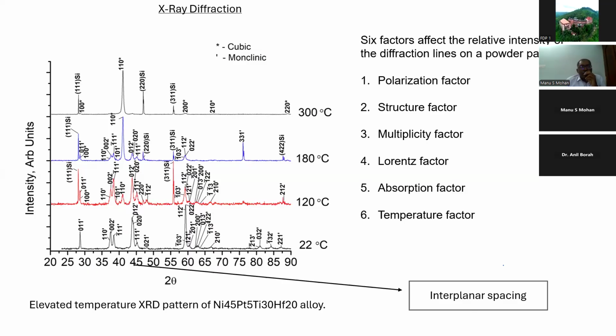Why are there a lot of peaks? Because it is a low symmetry phase — it is a monoclinic phase. Whereas when you have a cubic phase, you get a very nice pattern, but unfortunately it is not cubic, so you don't have those fine peaks here.